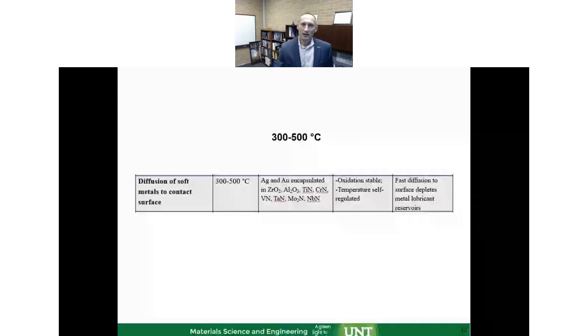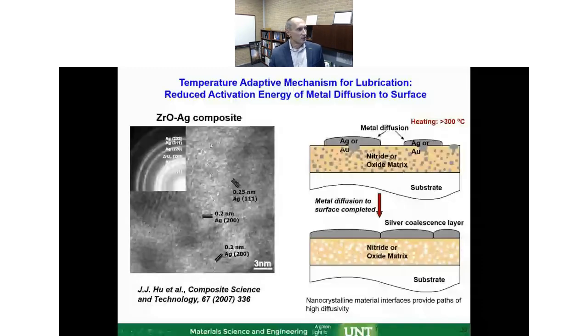Let me move here to the 300 to 500 degrees C range now in the mechanism, and we talk here about metals, because now the chalcogenide will be oxidizing, and they don't really survive at this type of temperature. As I already mentioned, maybe fullerene structures can extend it, but in general we now have to use some different mechanisms. One of the mechanisms we can use is gold and silver encapsulated in matrices. Those are an interesting concept, because you can take one of these temperature-stable oxides, such as zirconium oxide, or you can use nitrides, I'll show you an example of nitrides too, and put the soft metals there, distributed between the grain boundaries, or even in the defective crystal lattice itself.